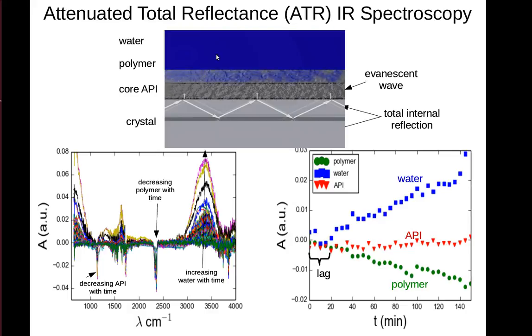We begin the experiment. We add water to the top surface. The water penetrates through the polymer into the core. As the experiment proceeds, we should see an increase in the intensity of absorption at the water band, and then a decrease in the absorption of the polymer band, and a decrease in the absorption of anything that's being dissolved in the core material. The bottom left shows the absorption as a function of wavelength, with multiple spectra collected over time.